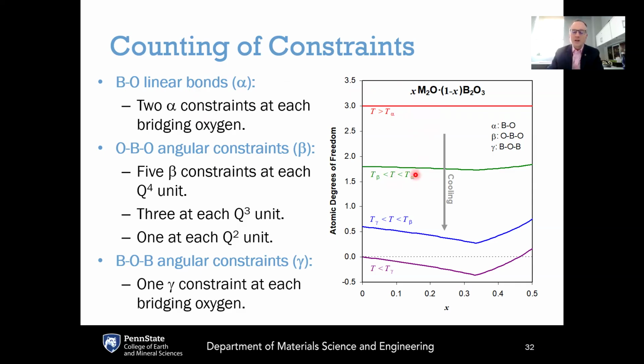That means that the alpha constraint, the strongest constraint, is rigid, but we're still at temperatures above T beta, so above the second strongest constraint. The second strongest constraint, T beta, the next one, is the angular constraint around the cation. So this is the OBO angular constraint. There are five of these at each Q4 unit in a tetrahedron. There are three of these at each Q3 unit in the trigonal configuration, and then only one of them in a Q2 unit. And so when the system is then cooled below T beta, we go from the green line down to the blue line. And then if you continue to cool, the next strongest constraint is the angular constraint around the oxygen, the BOB constraint, and there's one of these at each bridging oxygen, and that would take us from the blue curve to the purple curve.